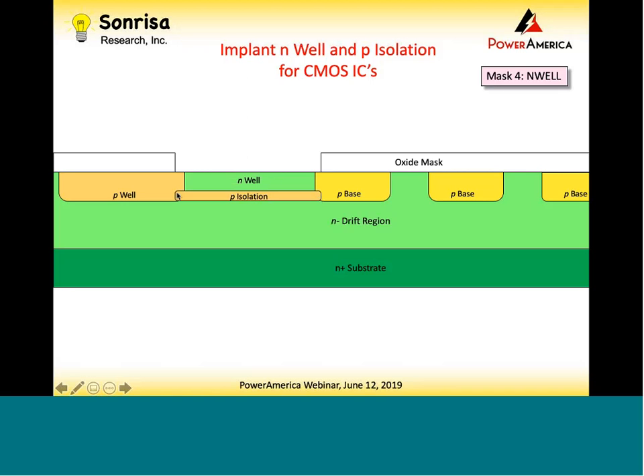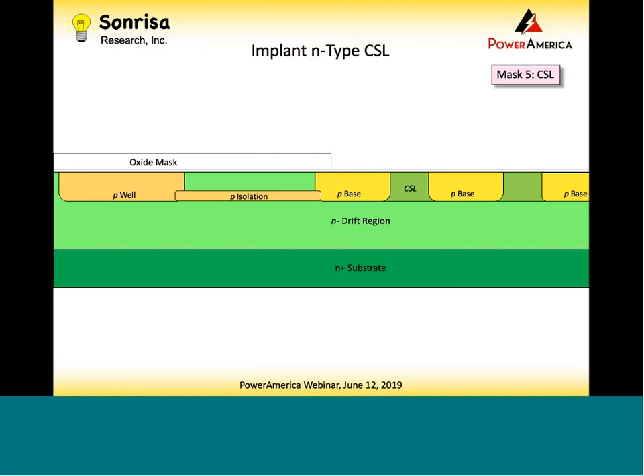So what this does is this N-well is isolated from the high voltage in the region below by this P-N junction that's formed here, and around the edges we're surrounding it with a P-well. So it's completely cut off from the high voltage, and it's in this N-well that we're going to build our P-channel MOSFETs. We may do a CSL or a JFET implant over here for our DMOSFET. We do the N-plus source implants. We use the same source implant for our N-channel MOSFETs in the CMOS and in our DMOSFET.